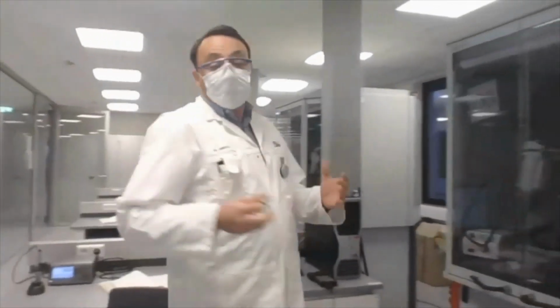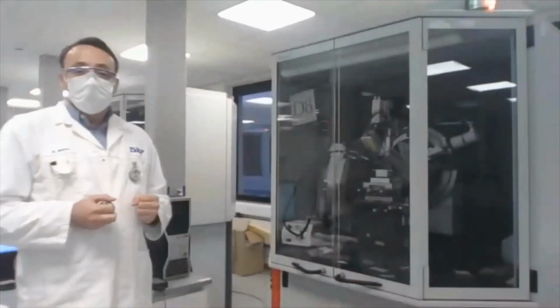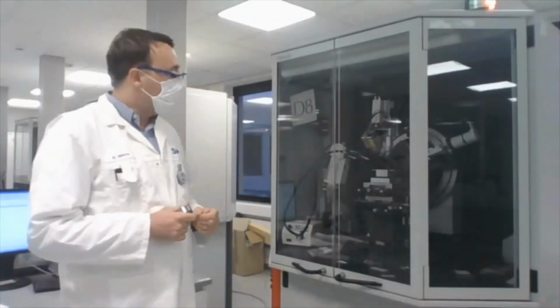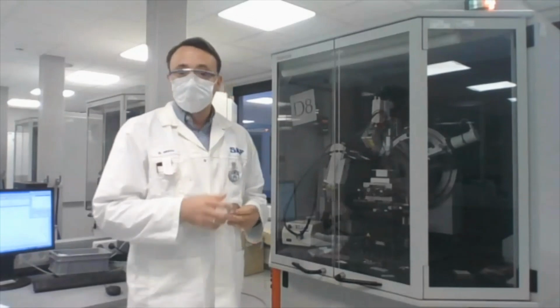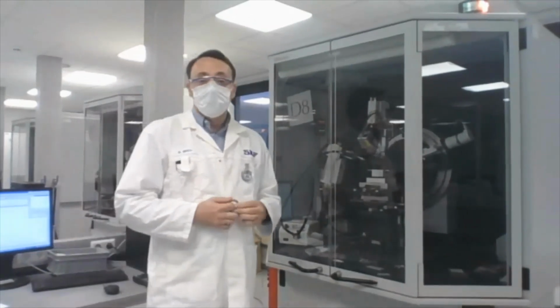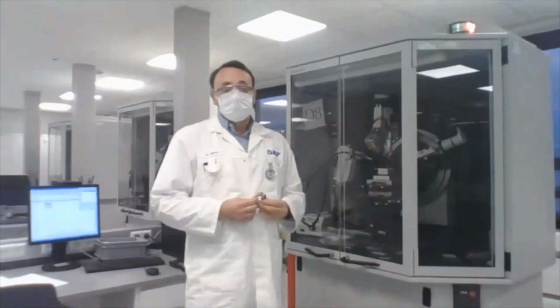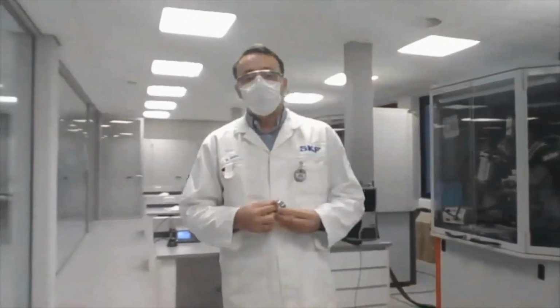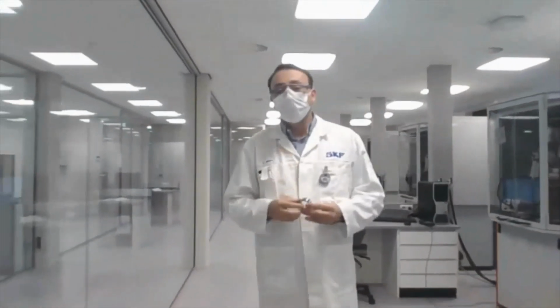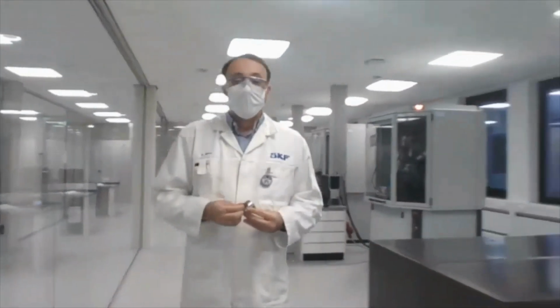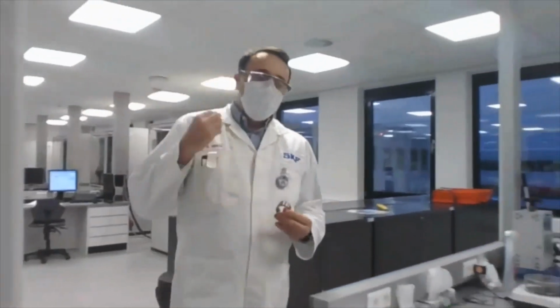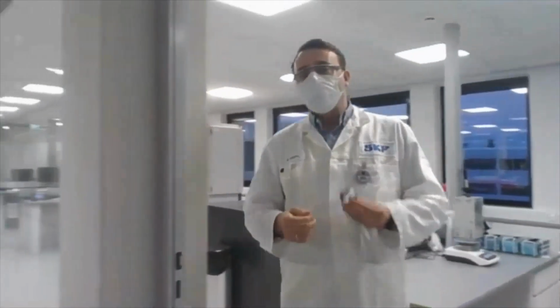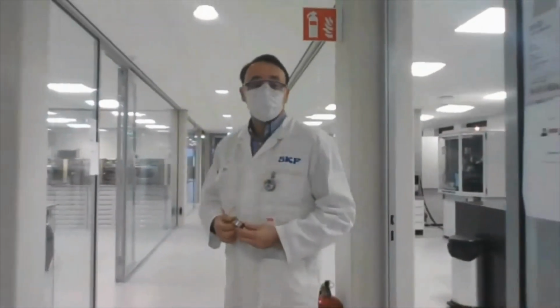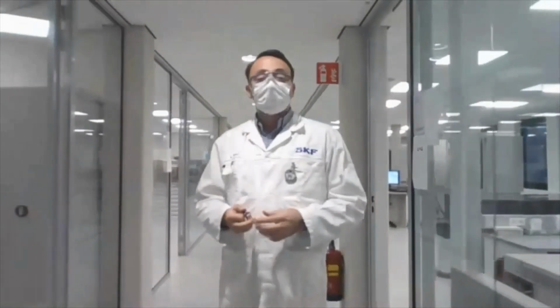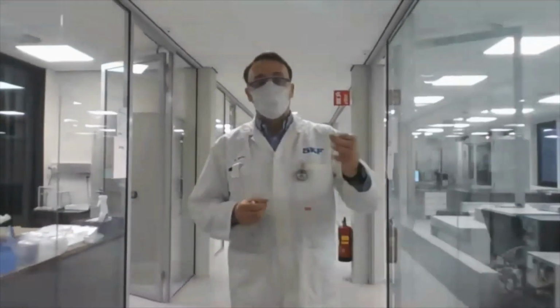Now, for example, in wind applications, stability of the bearings during operation depends on several parameters, one of which is, of course, the amount of retained austenite. Sometimes it is not only retained austenite and ferrite to quantify, but also other phases, like, for example, in machine tool applications. We are using this technique not only for investigations on bearings, but also sometimes on other component test specimens, and also on experimental test specimens like dilatometer. Now we are going there, where I will give you a small speech about that.